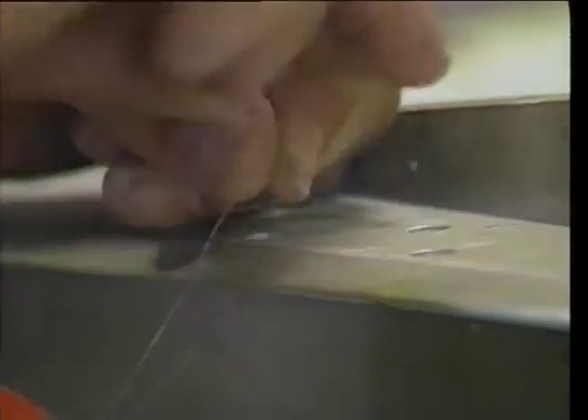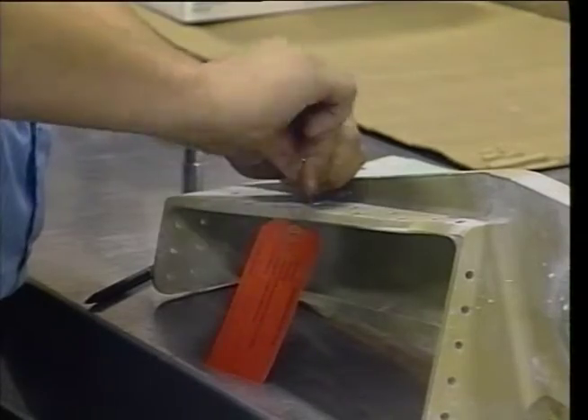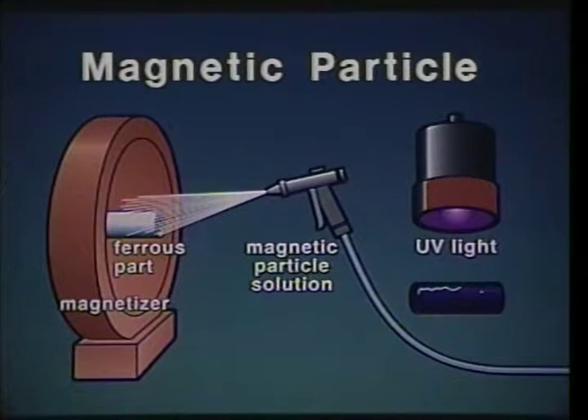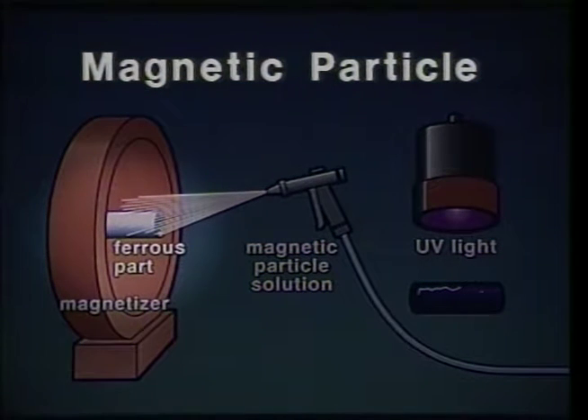Because this inspection revealed a crack on the interior surface of a bolt hole, this pylon bracket is tagged for rejection. If the part being inspected is susceptible to magnetism, it can be inspected by the magnetic particle inspection method. The process requires that the part be magnetized.